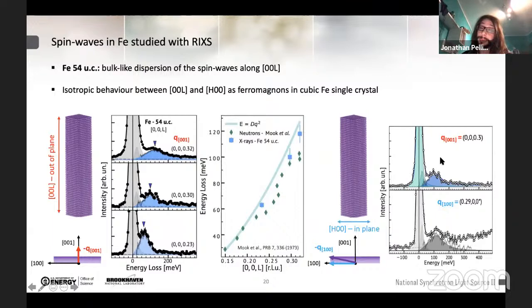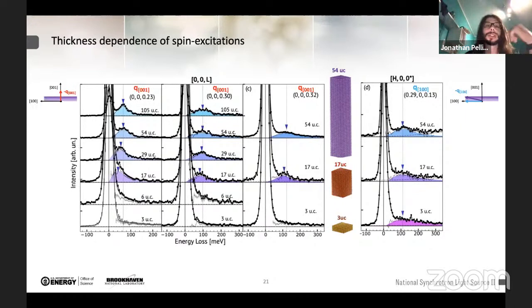However, now I want to introduce the concept of a thin film, because the next step will be to thin these iron samples, and then we want to identify the out-of-plane direction, which I will call 00L, and the in-plane direction, which I will call H00. So the next step of our investigation has been to perform this momentum-resolved investigation along 00L and H00 for different film thicknesses. Here I'm showing selected RIXS spectra.